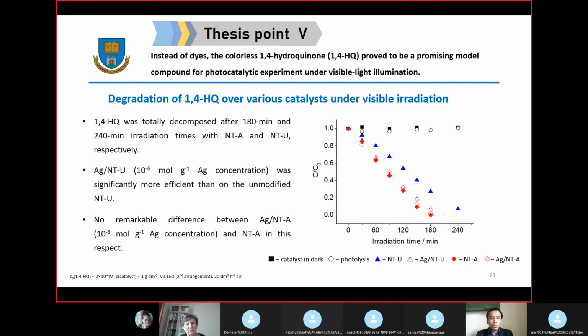The fifth thesis point: instead of dyes, the colorless hydroquinone proved to be a promising model compound for photocatalytic experiments under visible illumination. In the absence of the catalyst, as we see from this figure, the hydroquinone concentration was stable during the experiment, but when we put the catalyst in the photocatalytic experiment, the hydroquinone was totally decomposed after around 4 hours.